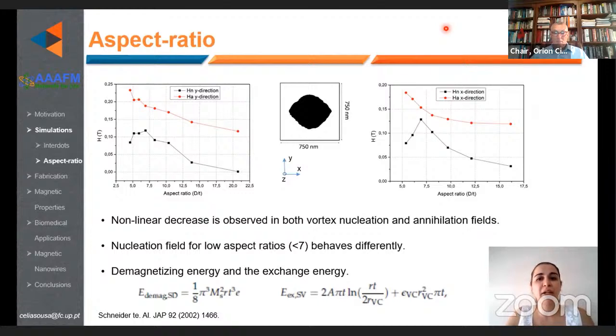This behavior can be explained due to the competition between the demagnetization energy and the exchange energy. However, in the case of nucleation fields for low aspect ratio, lower than 7, in both directions, they appear to not follow the same trend as the others. This is maybe associated with the lower limit of the behavior, when the assumption of thin disks falls short and the remnant state tends to the single domain.